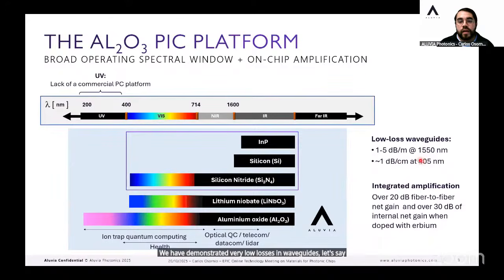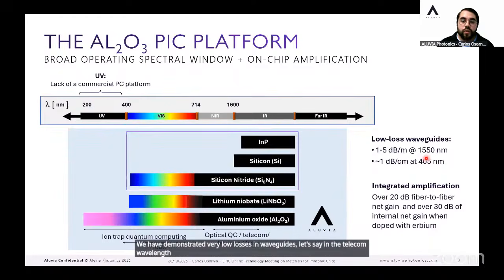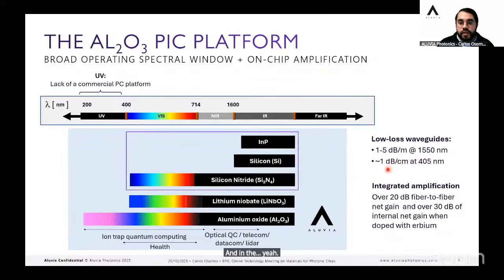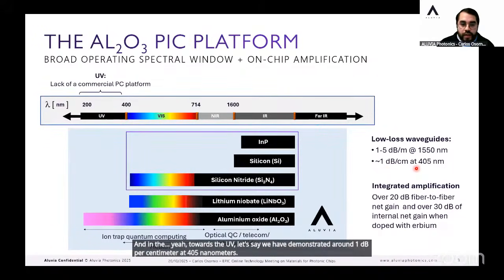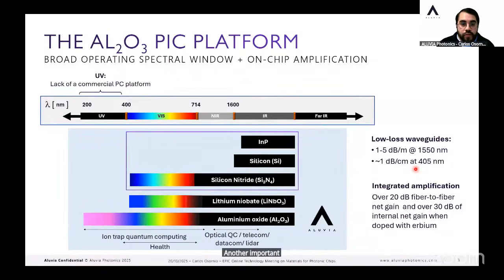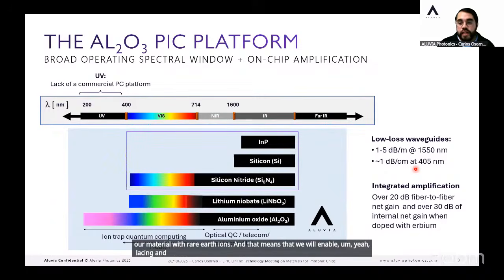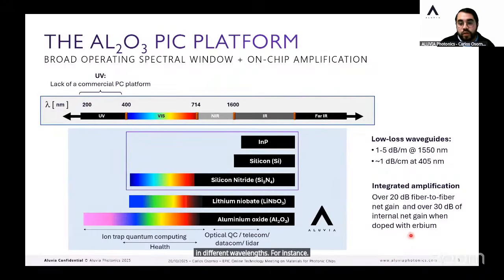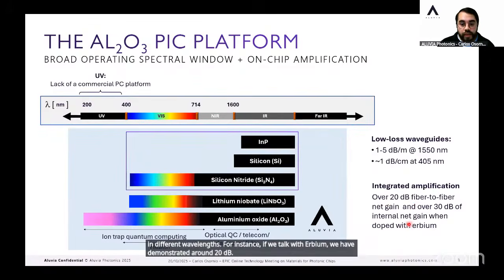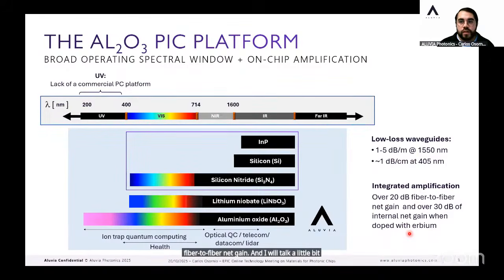In the telecom wavelength, we are in the order of 1 to 5 dB per meter. And towards the UV, we have demonstrated around 1 dB per centimeter at 405 nanometers. Another important advantage of aluminum oxide is that we can dope our material with rare earth ions, and that means that we will enable lasing and emission at different wavelengths. For instance, if we dope with erbium, we have demonstrated around 20 dB fiber to fiber net gain, and I will talk a little bit later about this.